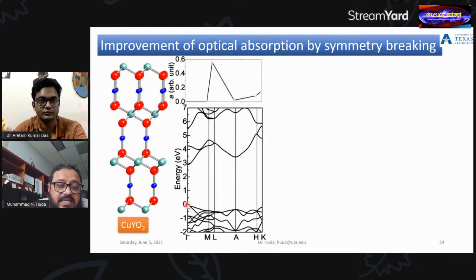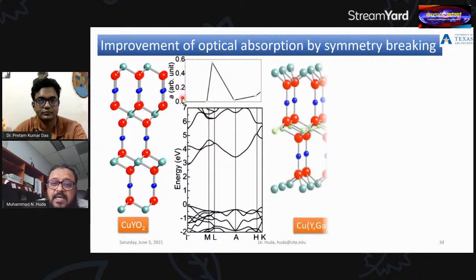And if we look exactly at the lowest gap, this is again optical absorption probability. Exactly at the lowest gap, absorption is exactly 0. So no absorption at the lower energy range. And again, this absorption is 0 because it is prohibited. The electron transition from the valence band to the conduction band at this point is prohibited due to some dipole selection rules. Now, those dipole selection rules are basically imposed by the symmetry of the crystal. So the idea of this work: let's break the symmetry. If we break the symmetry, then we should see non-zero absorption around this place. And this is what we did.